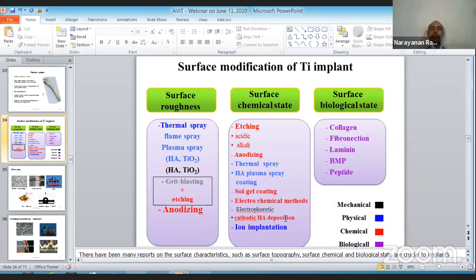Or hydroxyapatite can be coated on titanium implants to improve its surface chemistry and also enhance the bone bonding. You can also go for peptides, the protein coatings, or collagen or fibronectin, so as to improve its biological state. So my PhD was on this anodic oxidation and this hydroxyapatite deposition. This is a very inexpensive technique.